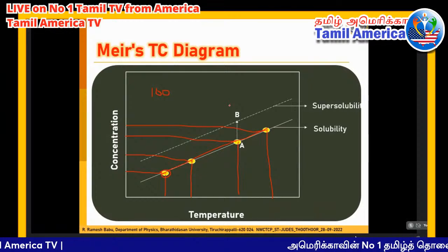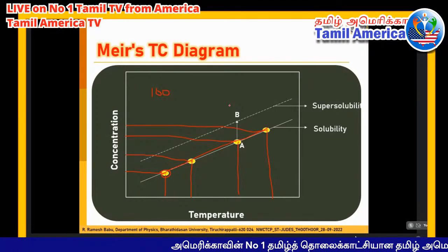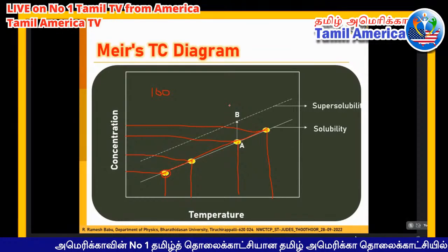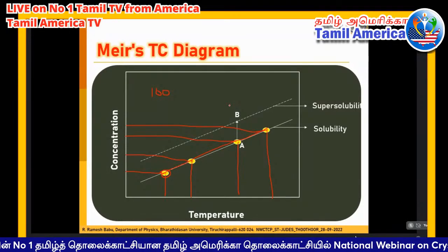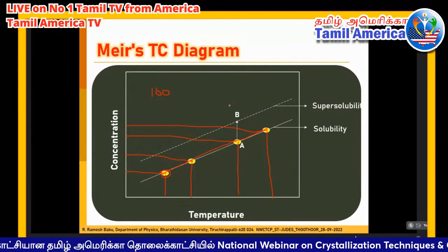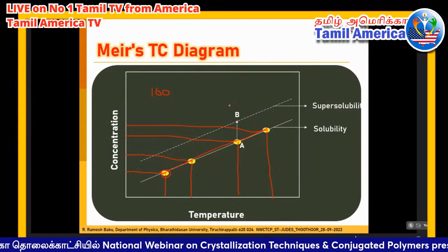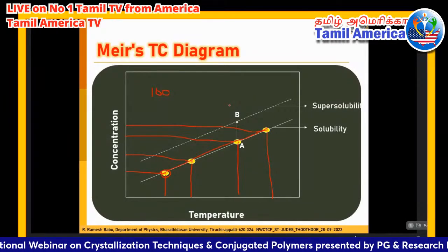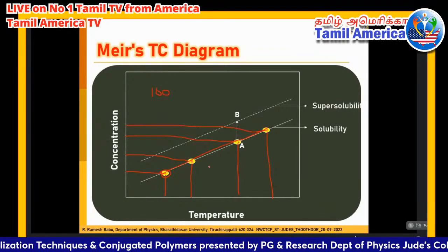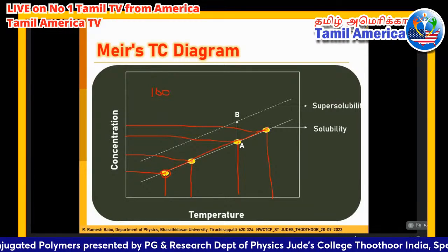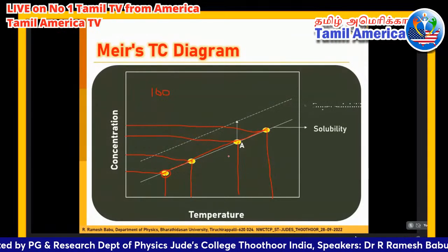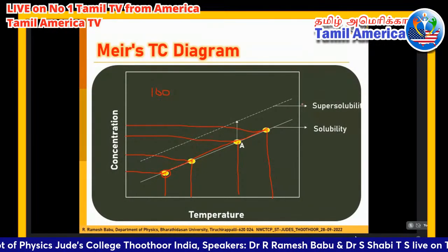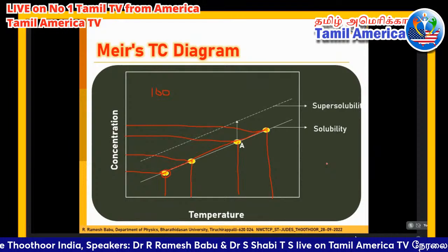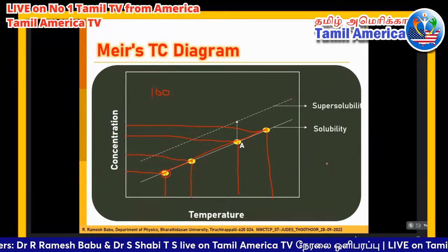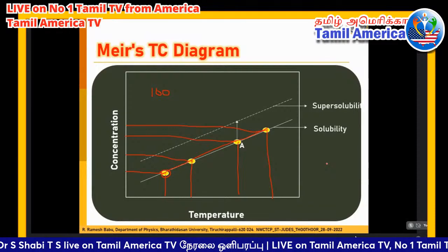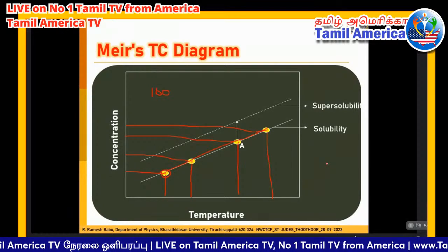So we have achieved more than equilibrium concentration. This is called a super solubility of the solution, achieved by evaporating the solvent, the slow evaporation method. You can do the same experiment at different temperatures, and when you connect all these points, we get this type of curve, called the super solubility curve. This is one of the low temperature solution growth techniques, the slow solvent evaporation technique.